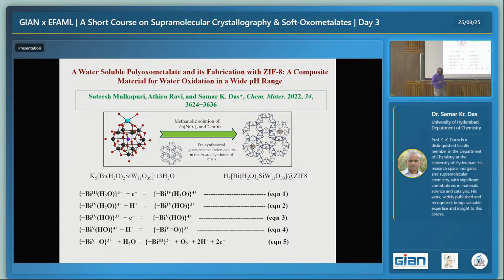Not only that, a miracle happens. The compound which decomposes at neutral pH slowly within 15 minutes or so is stable here forever. Forever means at least weeks and weeks and months and months. Nothing happens once you put it inside.